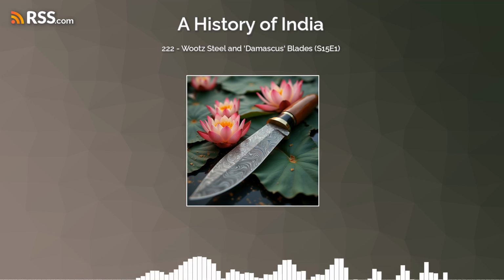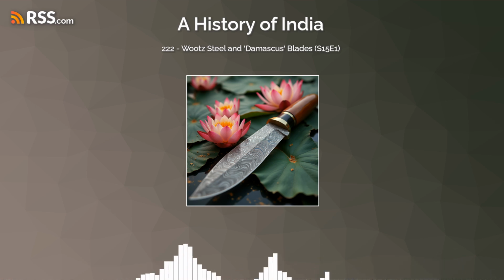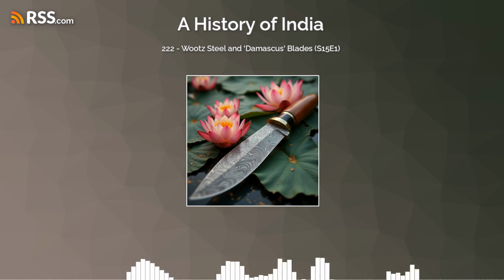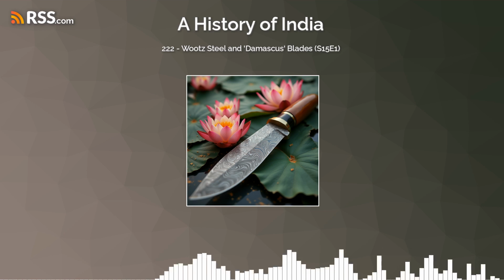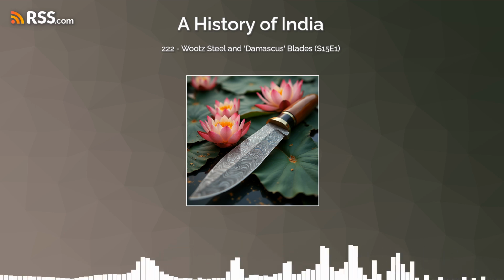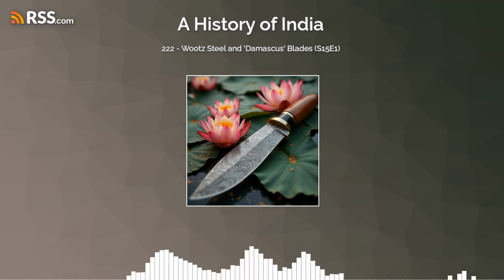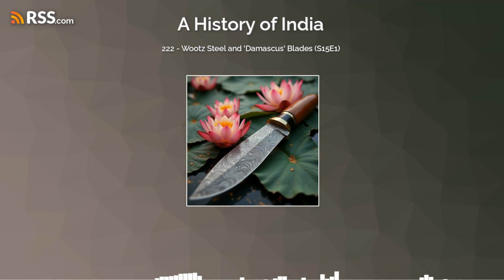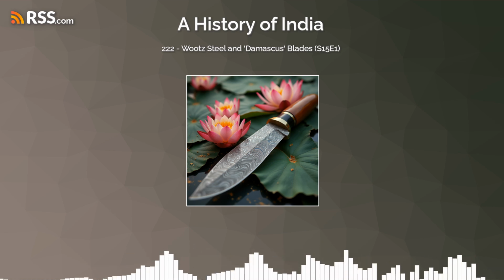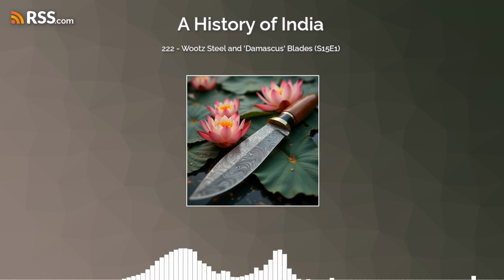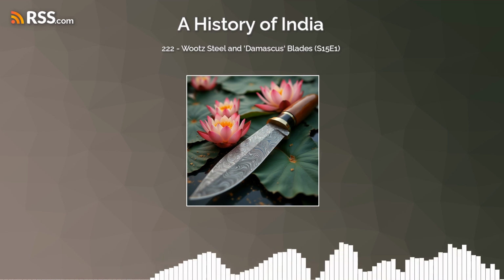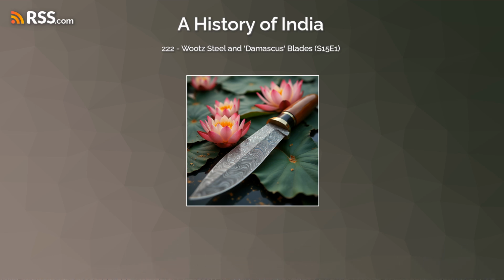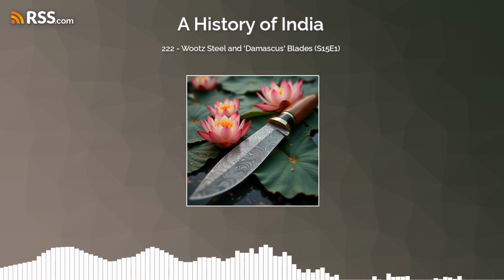And even cooler, sometimes they find tiny metallic beads, globules of steel trapped inside the glassy, vitrified walls of broken crucibles. Microscopic analysis of these globules confirms they are indeed high-carbon steel, typically 1.3–1.5% carbon, with microstructures like cementite networks around pearlite that perfectly match what you'd expect from this crucible process. It's direct metallurgical fingerprinting. And finally, the finished products, the actual historical blades.